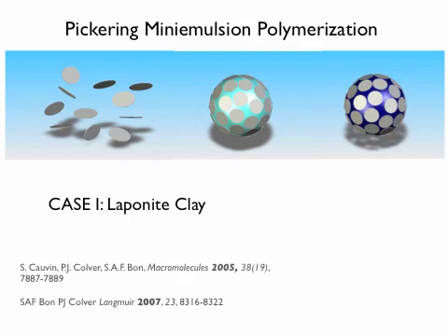So these particles can decide to sit in the water phase, they can decide to sit in the oil phase, or they can decide to sit at the interface. Now, in order to stabilize an oil droplet in water, the particle has to be relatively hydrophilic, and it basically likes to sit more in the water phase. So you could argue that if the particle is relatively hydrophilic, it's either in the water phase or on the interface, but it will never be in the oil phase. And that's a relatively good assumption to make.